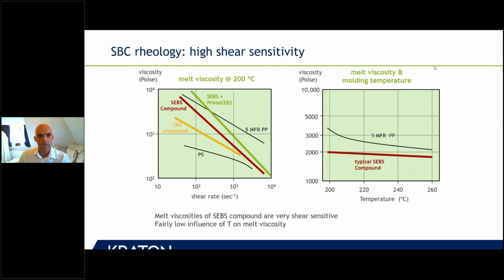One of the key things that I touched upon already a little bit is the rheology of styrenic block polymers, and the key thing here is that our polymers are very shear sensitive. If you work at a certain temperature, for instance, I'm showing the melt viscosity here at 200 degrees, the effect of increasing shear is much higher than for, for instance, a polystyrene homopolymer or a polypropylene homopolymer. You see a 5 MFR, so melt flow rate, polypropylene.